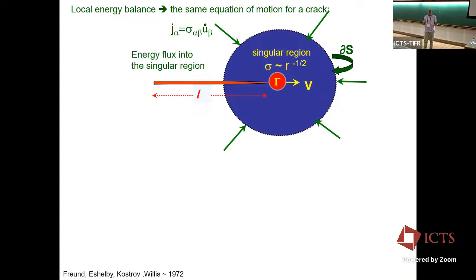So we're still talking about the same thing. We're talking about a balance of energy flowing into the crack. This balance can be either local or global like we did before, but it's the same thing. Now we're just zooming in, since we know what the singular fields look like, as we get very, very close to the singularity, we can ignore everything else and just look at the singular fields. And that's classically what people do in fracture mechanics. What I showed you was the unclassical way fracture mechanics was derived in the first place.